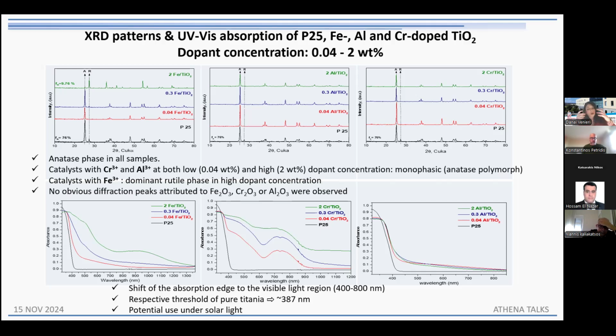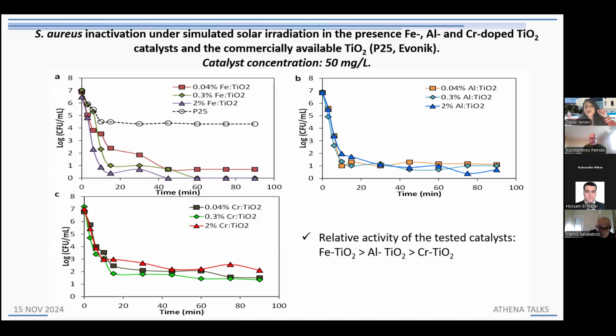So according to those diagrams and to the overall characterization of the catalysts, there was a potential of using them under solar light, either simulated or natural. And actually, this was what we achieved. You can see here the Staphylococcus inactivation using all those catalysts and the commercially available titanium dioxide, the P25. Of course, we tested many different concentrations of the catalyst. And just to point out here that the highest concentration of the catalyst does not mean that it is the best one. No, because the highest concentration of the catalyst, we're talking about slurry phase,